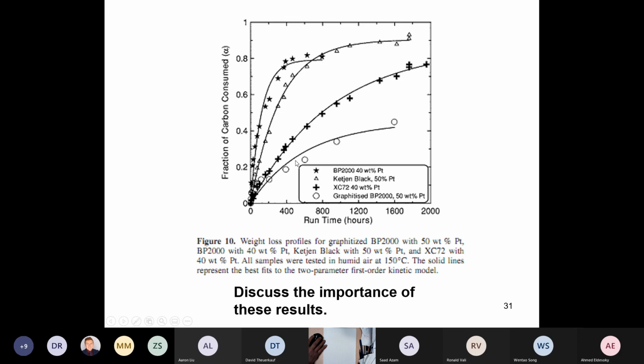The surface area reduced a little bit, but mainly the idea of doing this was to try to create a carbon with more satisfied bonds at the surface where you would have less reactivity. So this graphitization of the carbon became a fairly important step in the production of these carbon-supported catalysts for fuel cells.